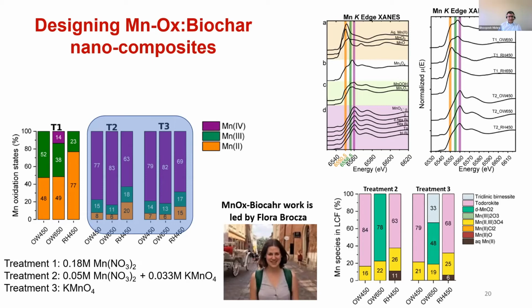So what we had is, for manganese treatment 1, it was mostly manganese 2 and 3. But treatments 2 and 3 led to mostly manganese 4, as you can see. And then we went to do a full-blown analysis to understand what was happening in the overall manganese, not just oxidation states, but what kind of phases of manganese those were. And we saw here that basically we had all kinds of different species of manganese.